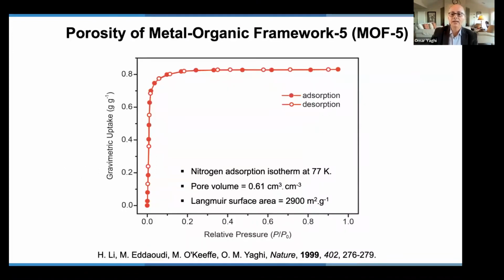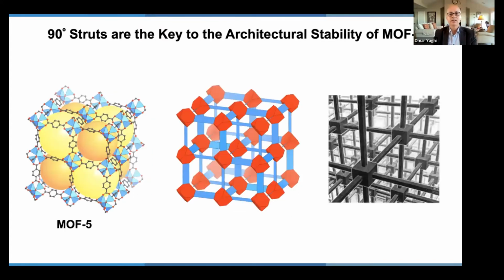This is MOF 5, and you can see here, using gas sorption isotherm, one can derive the pore volume, which is 61% of those crystals is open space. And that corresponds to a surface area of almost 3,000 meters square per gram. That's basically, in 1 gram of material, you have the surface area of an entire football field. And that's the space onto which you can then stack hydrogen or carbon dioxide or water in terms of achieving the clean energy, clean air, and clean water objectives.